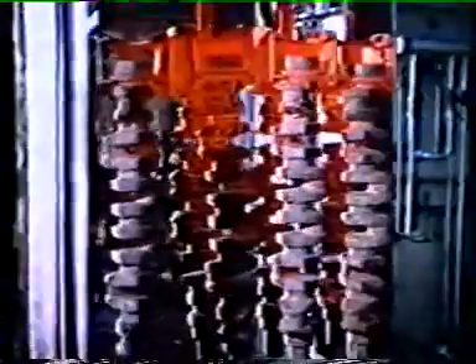Here is a batch of plain carbon steel crankshafts about to be quenched. It is poised above a tank containing cold water. The crankshafts remain in the water for only 3 minutes. Then they travel into the tempering furnace, which is controlled at 550 degrees centigrade.